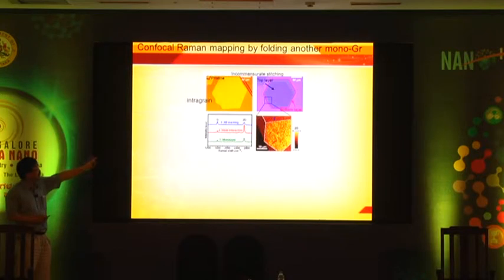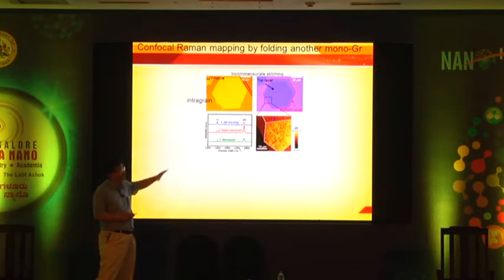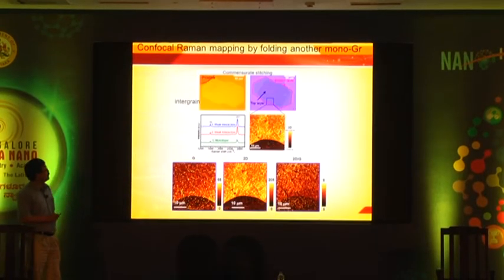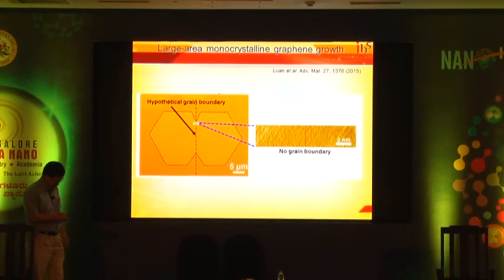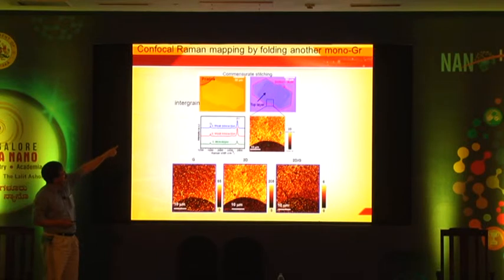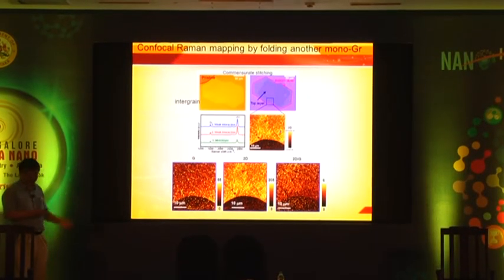There are several examples to demonstrate this concept. Using Raman spectroscopy, you can identify the formation of this grain boundary. I'm not going to go into details, but when these graphenes are stacking, we can stack these graphenes together. There is heavy stacking, when there is a twist, and there's a monolayer. You see this G to 2D band intensity ratio changes very consistently. We can take advantage of it and have a mapping, and you can see contrast ratio. If there is a contrast ratio, this means it is not a single grain, it is multi-grain. So we can actually prove it. When these are two graphene flakes in the same orientation, you see there's no such grain boundary. So you can also identify this using confocal Raman mapping.